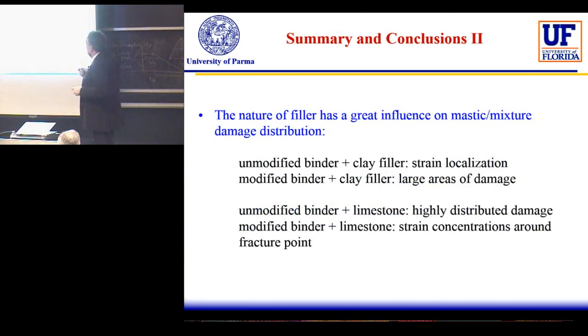Some consideration here on the fact that the nature of the filler has a great influence on the mastic and mixture damage distribution, and we can synthesize that unmodified binder plus clay filler has a different strain localization. When we have modified binder and clay filler, we have a large area of damage, a more distributed damage. Unmodified bitumen plus limestone has highly distributed damage, and modified binder plus limestone has more strain concentration around the fracture point.